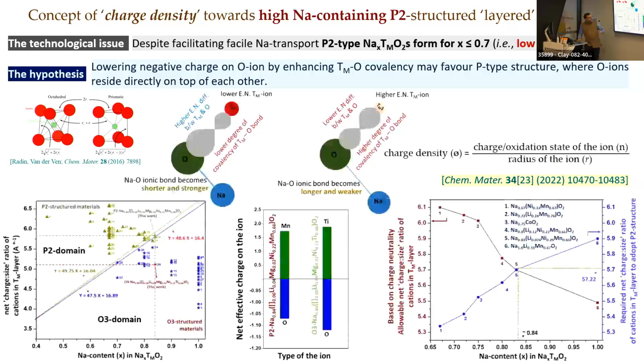Now by increasing the charge to size ratio, or selecting a cation combination in my transition metal layer with a higher charge to size ratio. That will lower my effective negative charge on the oxygen ion, because it makes the transition metal oxygen bond a bit more covalent, and the electron cloud is polarized a bit away from the oxygen ion.